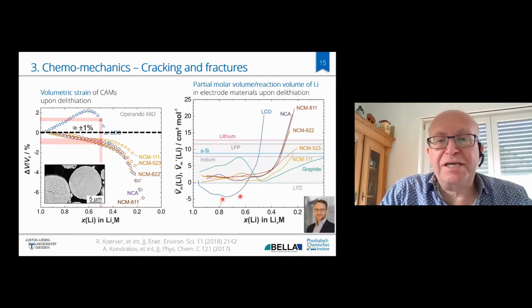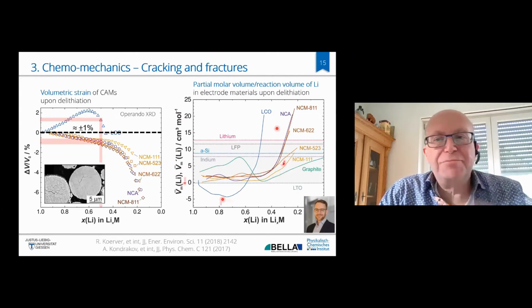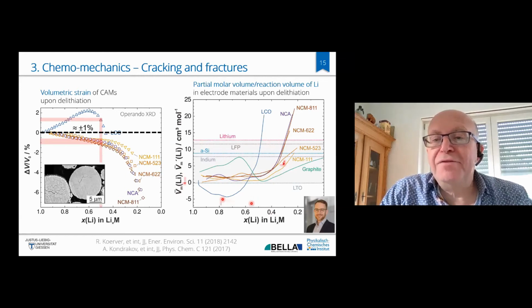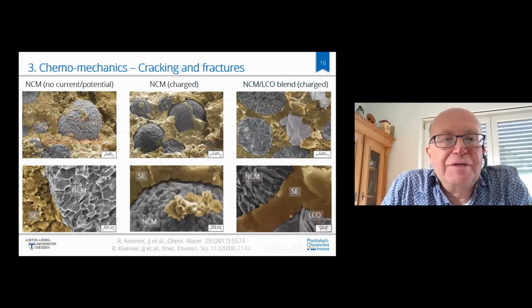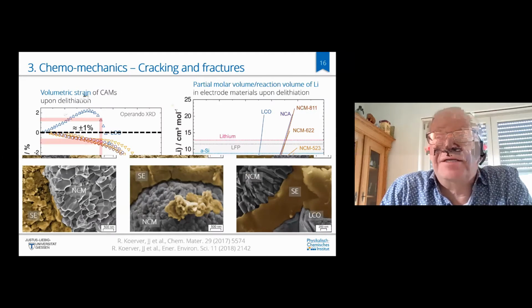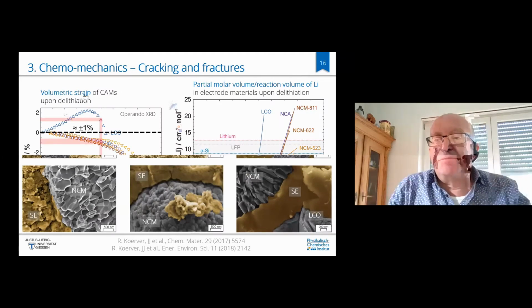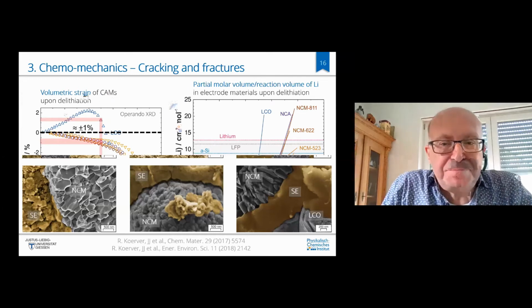This is just another representation of the volume effects by partial molar volume, where you see that in the extreme, the nickel-containing cathode materials really show stronger volume effects upon delithiation, in the region where they are already strongly delithiated, than lithium metal, for example. Okay, the effect, and this has been nicely shown by Raimund Koerver in our group, is that the cathode particles that originally have good contact, so this is a typical secondary cathode particle, lose contact after cycling. And you need external mechanical pressure to keep contact.